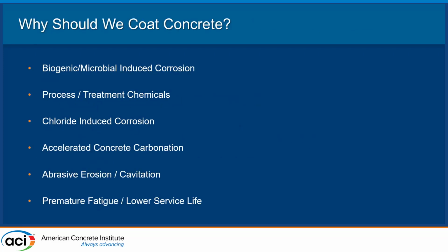So the gentleman before me talked about exposed concrete, and that's very popular, but there are situations where concrete needs to have coatings, whether it's biogenic, microbial induced corrosion, that we see a lot of in industrial environments, whether it's in the oil and gas industry or water, wastewater, where you have high levels of H2S, which react with the bacteria in the system, which consume that and generate sulfuric acid, which will degrade the concrete and erode it very quickly. Also, things in different environments where we have process or treatment chemicals that can erode the concrete as well.